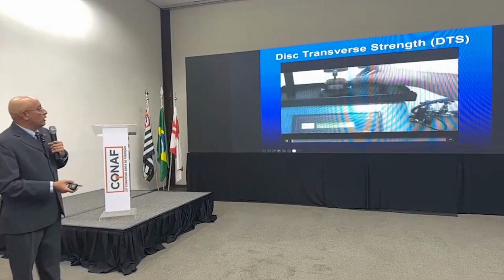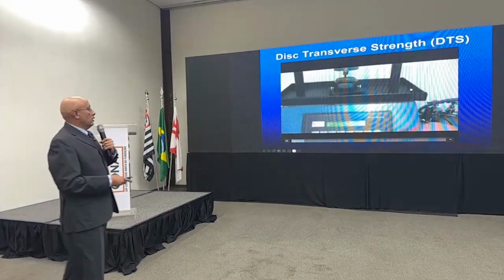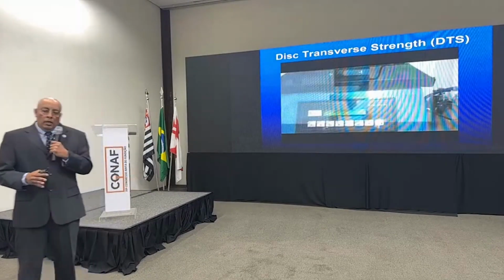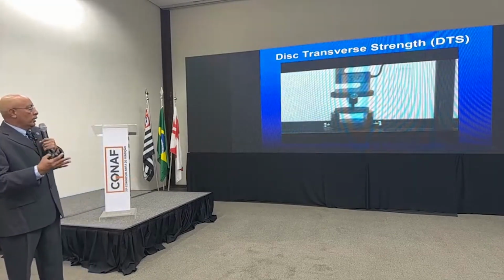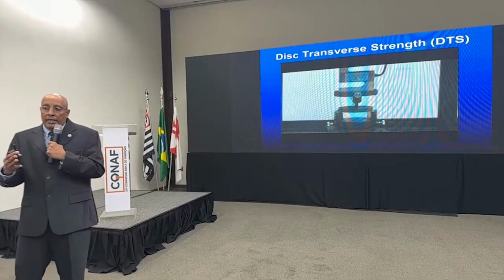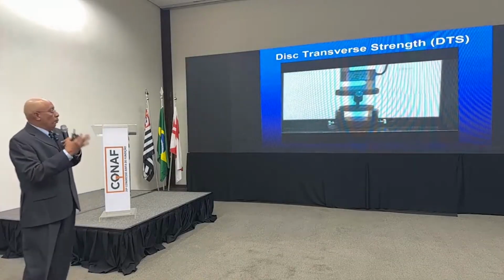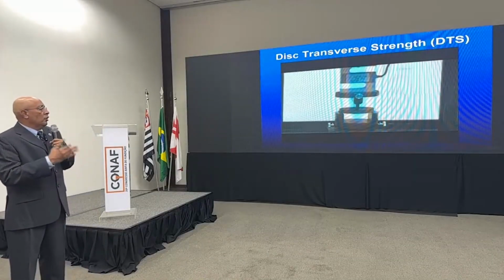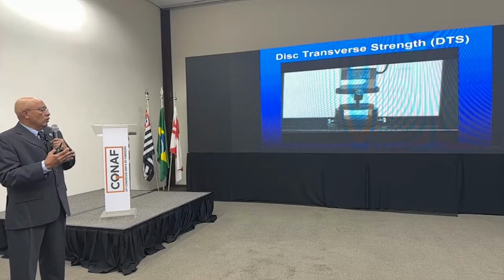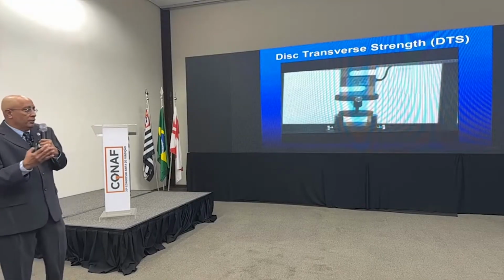This is the disc transverse strength test. This transverse strength, we don't place a lot of importance on this, but it does give us the mechanics. Why I say we don't place importance is because not too many cores or molds fail in compressive shear. More of it is impact.